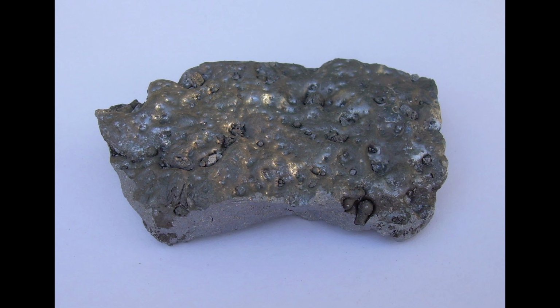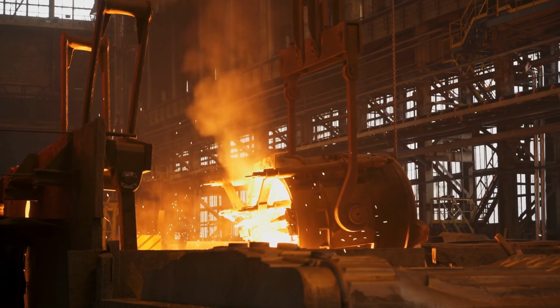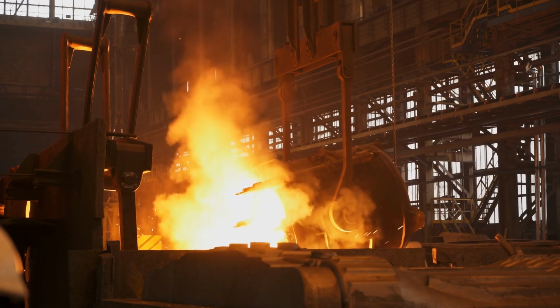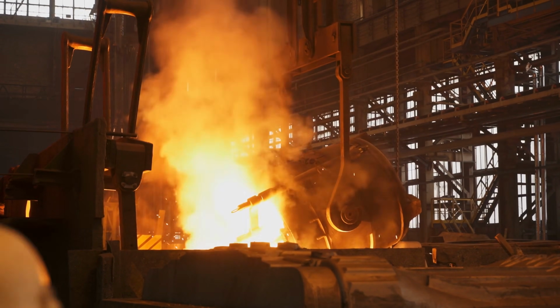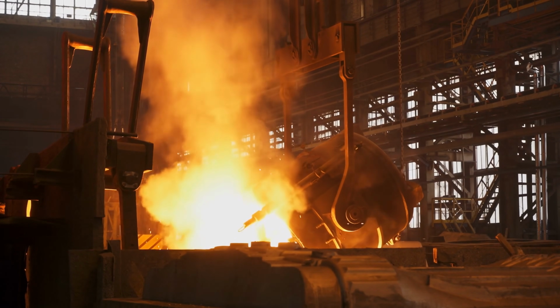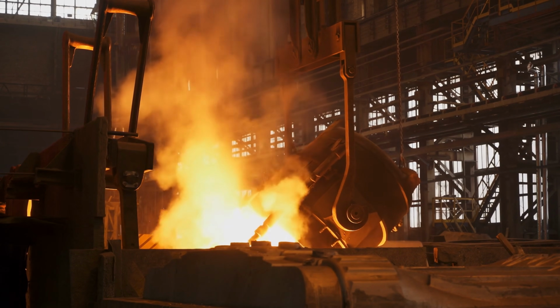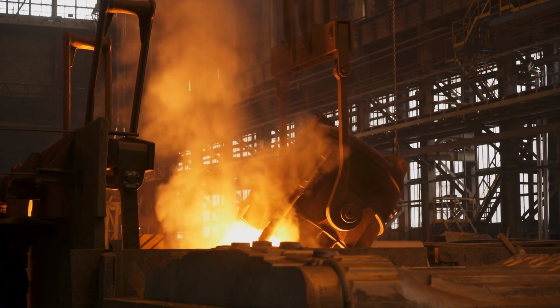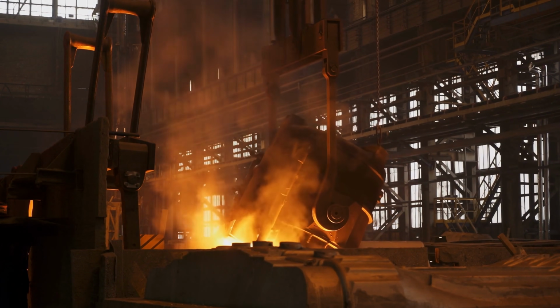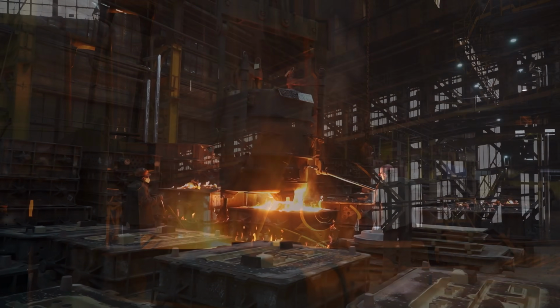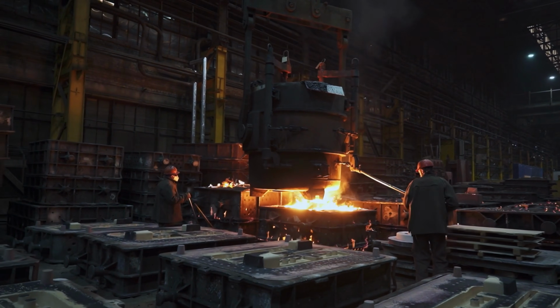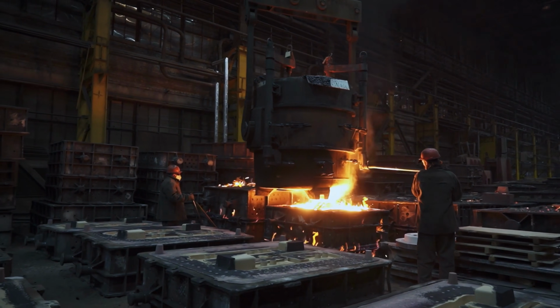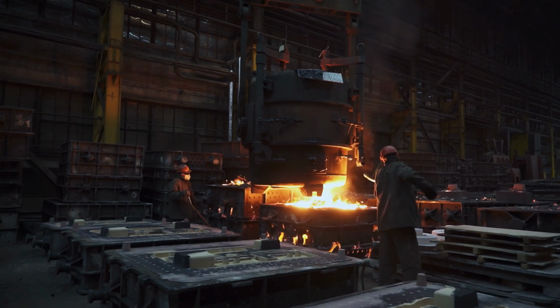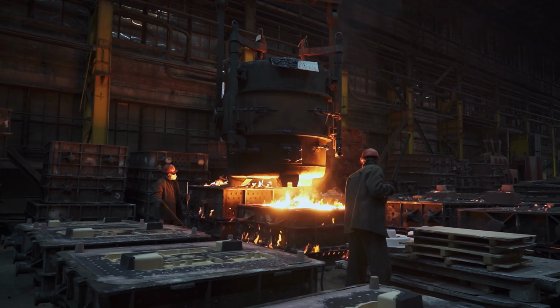If iron is present, the molten silicon will dissolve some iron and form an alloy called ferrosilicon. Ferrosilicon, usually 50 to 80% silicon with the rest iron, is easy to cast into ingots and is handy for steel making. In fact, roughly 80% of the elemental silicon produced ends up as ferrosilicon alloy for the iron and steel industry. China is by far the largest producer of silicon and ferrosilicon. Its factories churn out about 2/3 of the world's supply of silicon. Other big producers include Russia, Norway, Brazil, and the USA. If you've ever seen a giant shiny ingot being poured in an industrial video labeled silicon, odds are it's this impure silicon intended for alloys.